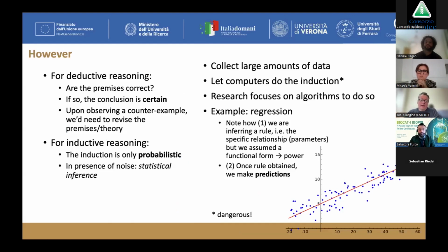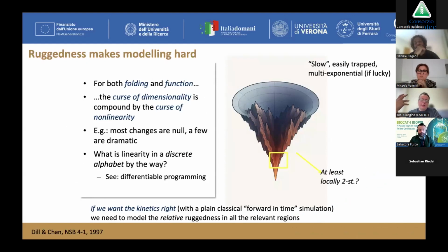How do we get to the data? Well, for example, my expertise lies in simulation, in all atom simulations. So we try to model complex systems in the most reasonably detailed way that can be simulated for times long enough. And it's cursed with the dimensionality problem and its nonlinearity, which means that, as probably you know even better than me, you deal with free energy landscapes, which are very rugged. So even if for a given protein or a given process the most likely state is unique, reaching that state even from a slightly different configuration is hard.